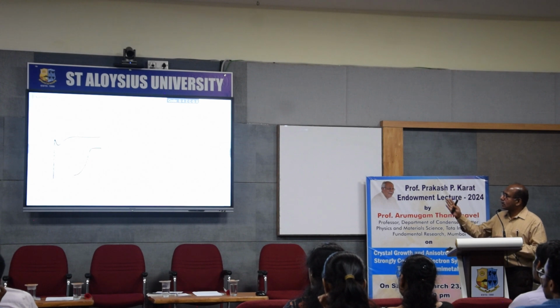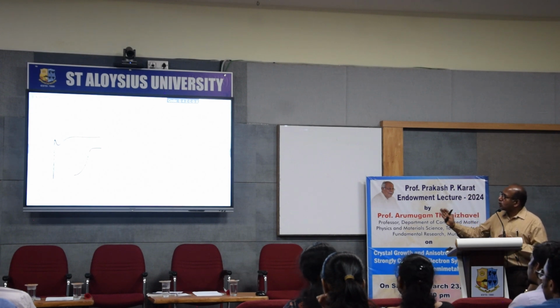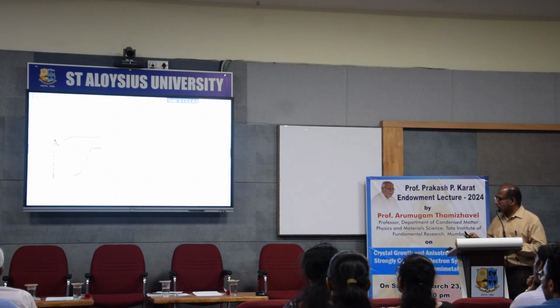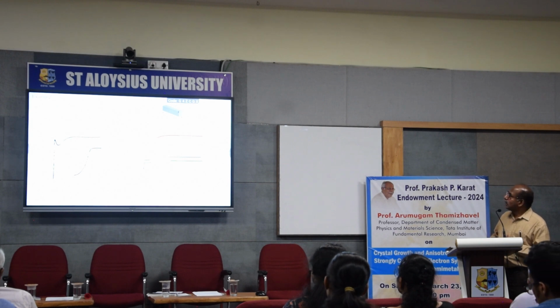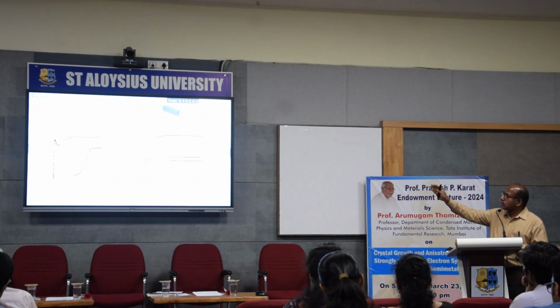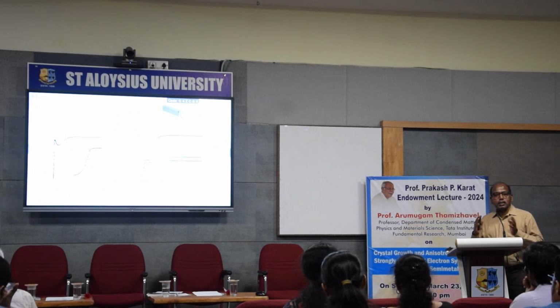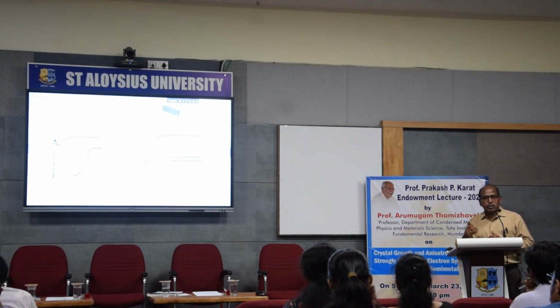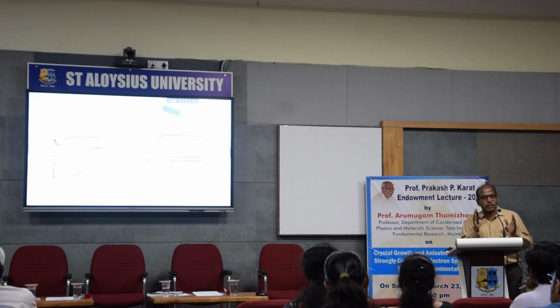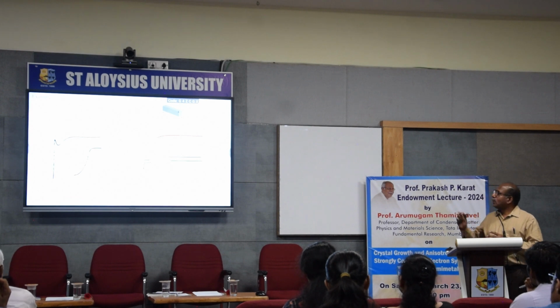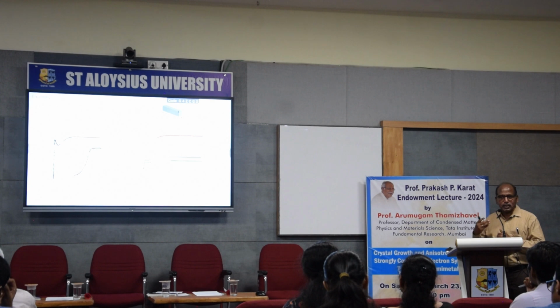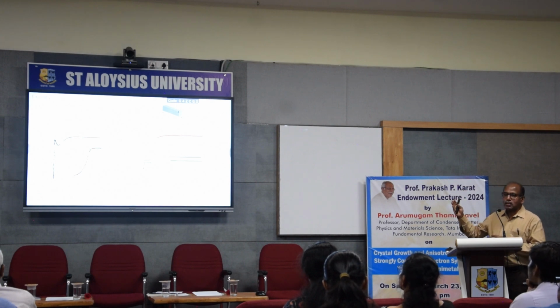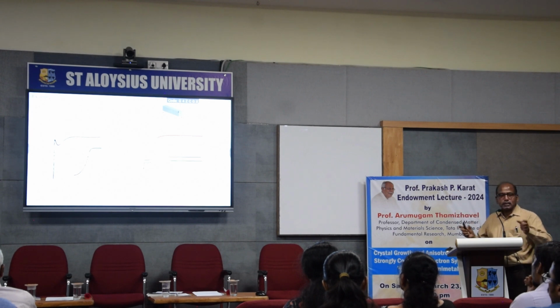When I measure the electrical resistivity, it looks like this. Quite weird, but don't worry about the shape of the curve. The point I wanted to make here is, if I grow a single crystal of this sample and do the same measurement on a single crystal, how will the electrical resistance look? So let's see that. I have grown the single crystal in my laboratory, and the crystal structure of this compound is orthorhombic. When I say an orthorhombic crystal, you can immediately imagine that a, b, c are not equal and alpha, beta, gamma are equal to 90 degrees. All these things are in the first chapter of Kittel, about the 7 kinds of crystal systems. So if I say orthorhombic, being a solid state physicist, or if you have studied solid state physics, you should immediately remember that a is not equal to b is not equal to c and alpha, beta, gamma equal to 90. When I say a is not equal to b is not equal to c, the unit cell will have different dimensions along the a, b and c directions.